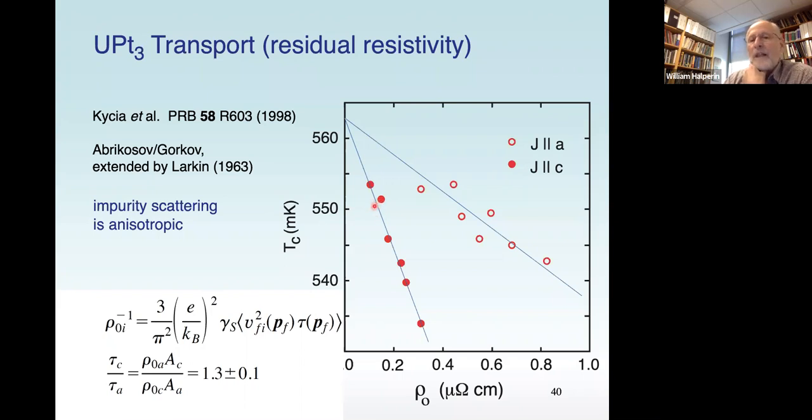Now, essentially all of these crystals shown here are just needles cut from the same crystal. After it's been annealed and fabricated, it's the same crystal, but different samples were then annealed at different temperatures. And the different temperatures have an effect on the zero temperature resistivity. You can vary it over a range of, well, more than a factor of 2.